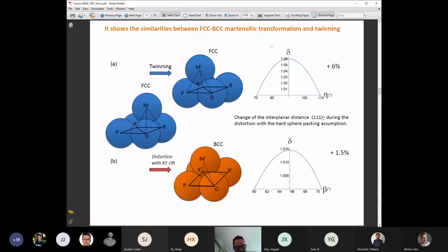It also helps you to make some links, for example, for the FCC to BCC transformation. FCC is at the left, and BCC is at the bottom in orange. And if you look, it's what is represented. It's the ABC stacking. You know that on the 1-1-1 plane, you can represent FCC by an ABC stacking. If you look at the first layer and the second layer, I represented an atom M in the second layer. And if you just move the atoms without changing the layer, you create a twin. You change the stacking ABC into ACB.